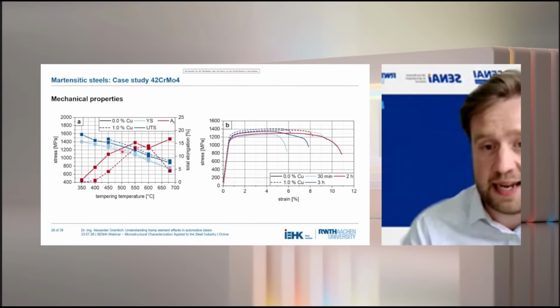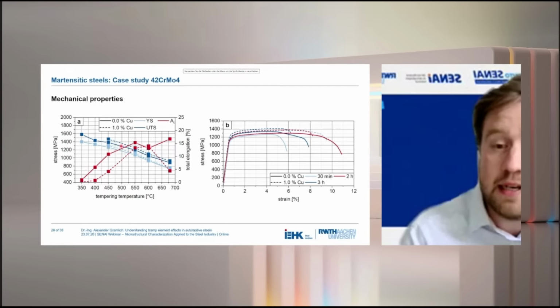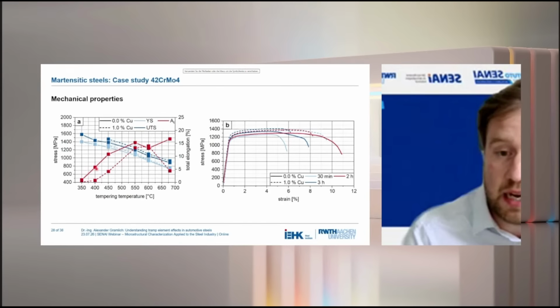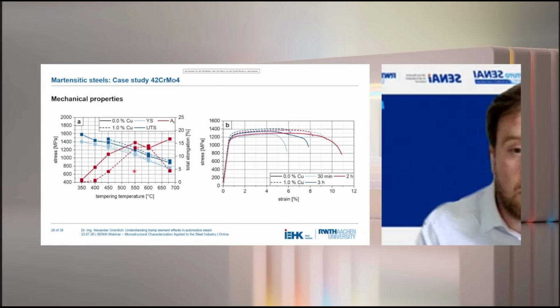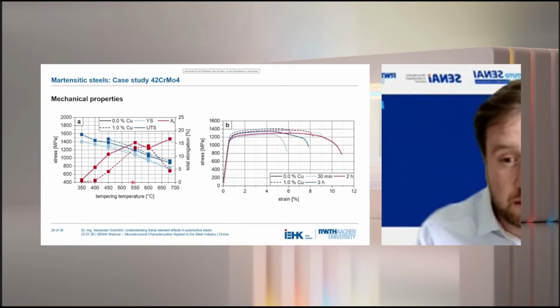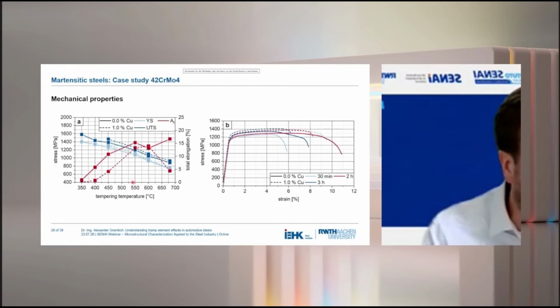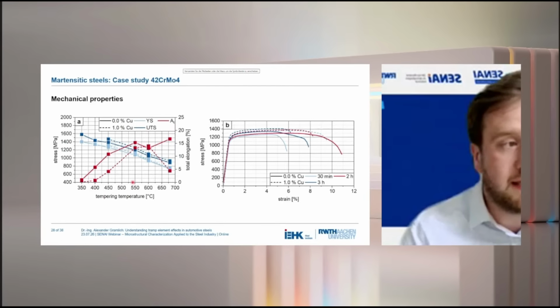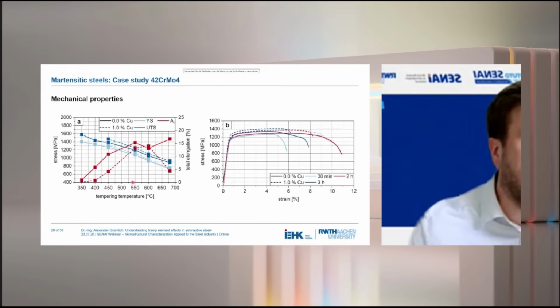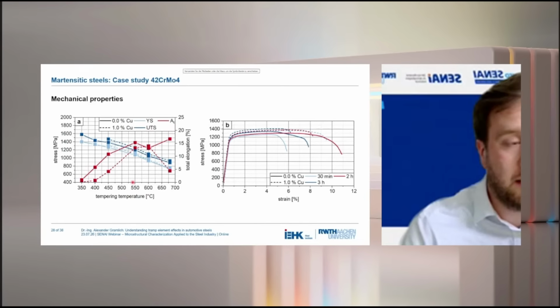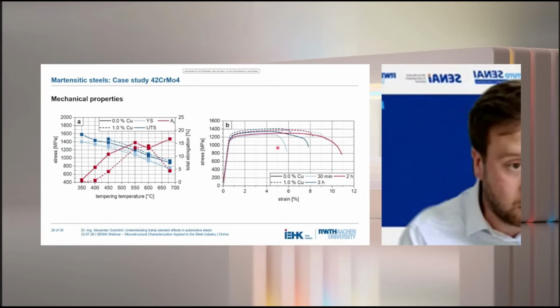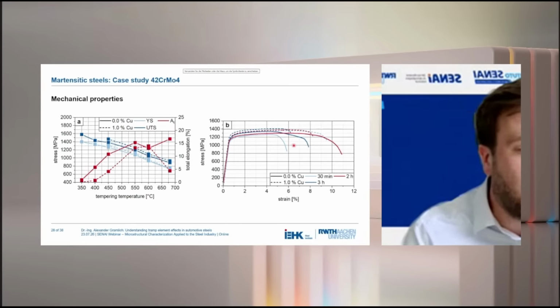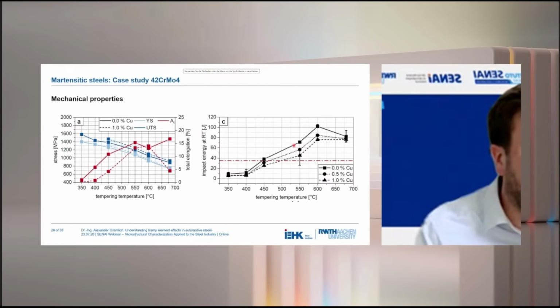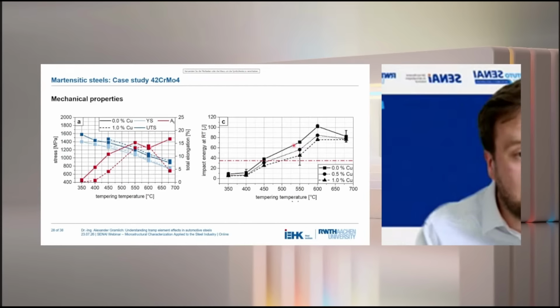When we are then investigating the mechanical properties, we can see here in the full line the reference alloy, and in the dotted line the one with 1% of copper. We have differences independent of the tempering temperature, however not critical. And in general, we always have the classic trade-off: higher hardness, lower ductility. Also, the general tensile test curves are quite similar. And the same can more or less be said for Charpy tests.